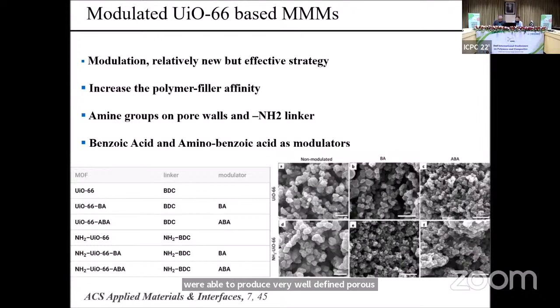We went ahead, instead of using post functionalization of sulfonic acid groups, in the extension of this study, we introduced CO2-philic groups such as amines and sulfonic acid groups, and we did this by using functionalization within the MOF. So we used a modulation approach. We used linkers comprising these CO2-philic groups, and we introduced them in the framework to produce modulated UIO66 based membranes. And finally, we synthesized membranes and tested them for gas separations, which I will share in a few slides.